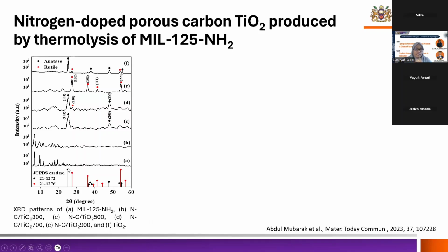This is without any calcination. And then as we increase the temperature of the calcination from 300 to 900, we observe the transformation of the MOF from MIL-125 into titanium dioxide. So at the top here is the XRD spectra of the commercial titanium dioxide, and we can observe that at 900 degrees Celsius, the titanium dioxide being produced is almost similar to the commercial titanium dioxide. In fact, we have obtained two crystal structures inside this titanium dioxide that we calcined, which are anatase and rutile.